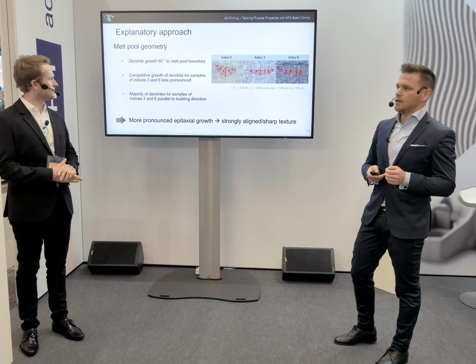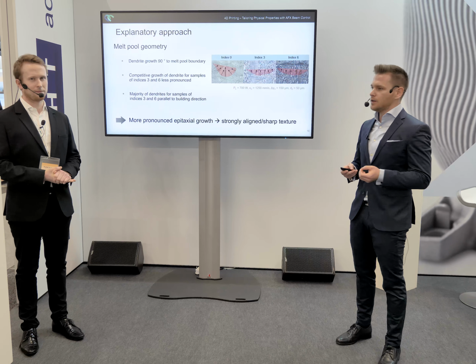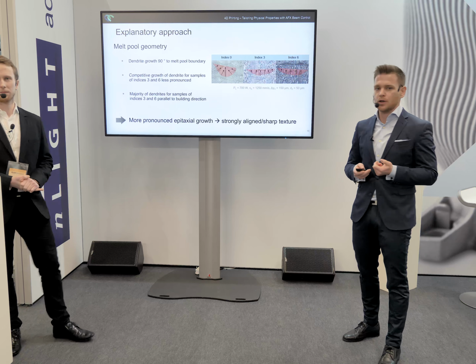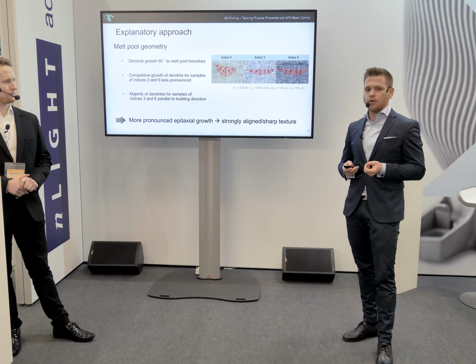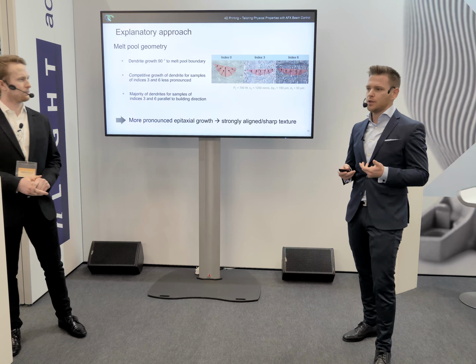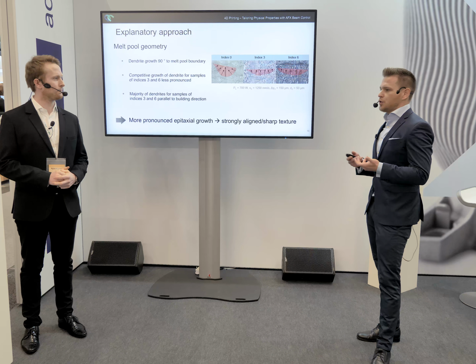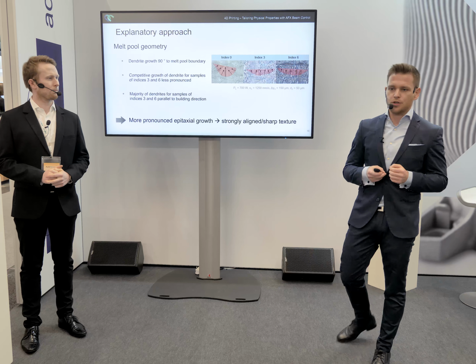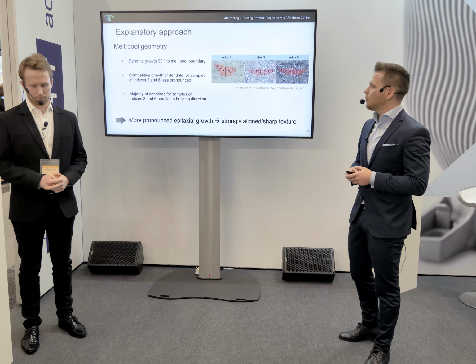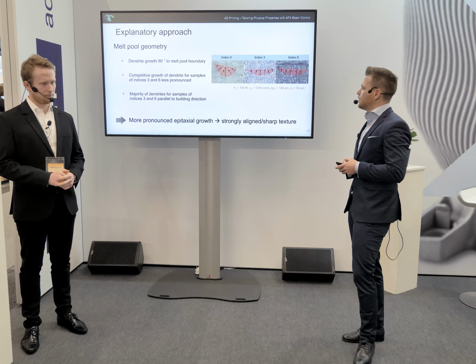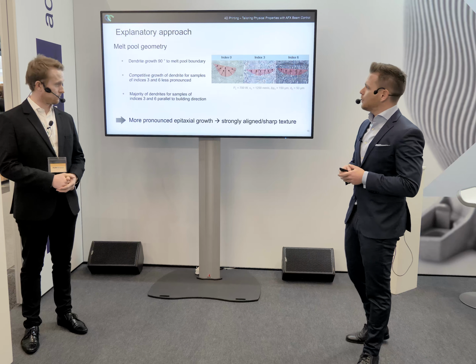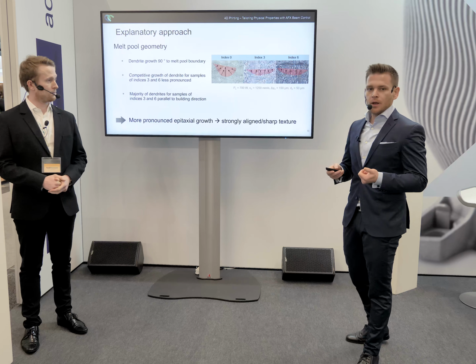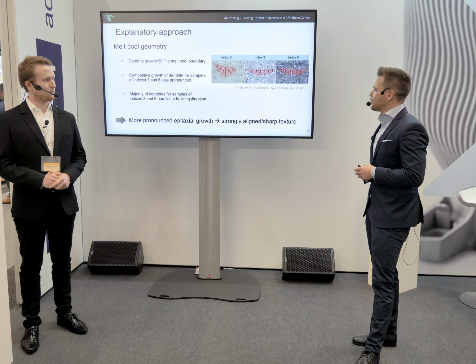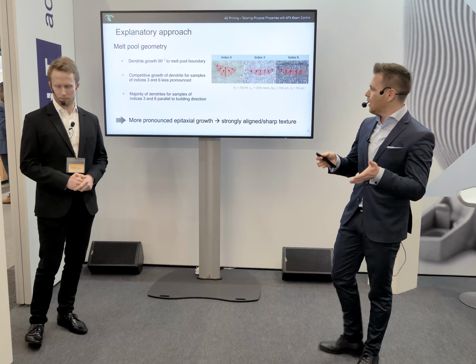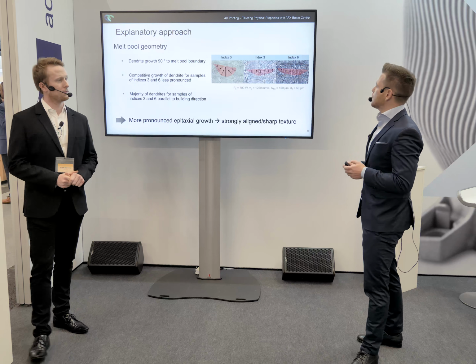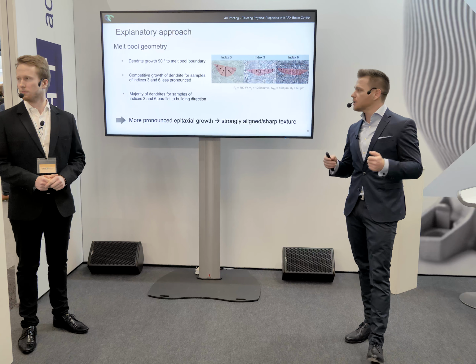One approach was that the microstructure was the reason, but as we have seen before, there was no big difference in the microstructure in terms of PDAS and segregation behavior, which are a direct consequence of the thermal history. And thus the assumption came up that there might not be that different a thermal field when using the different intensity distributions. One explanatory approach could be the melt-pool shape. As we may see here on the left side, the melt-pool shape of index 0 is much narrower and deeper in comparison to the sample of index 6, which is much wider and flatter.